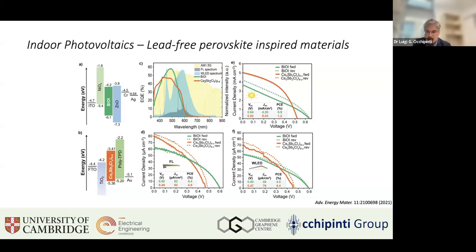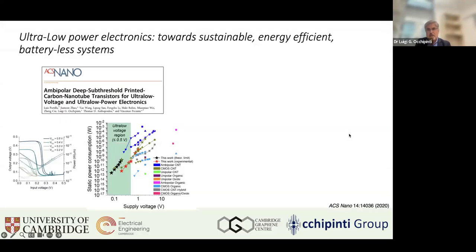Of course, in terms of efficiency, we can't compare this material with the lead-halide perovskite base. It only works when you have to power a very low power consumption unit or electronics. For this reason, we also explored ultra low power electronics. In this work, we reported back in 2020 ultra low power printed electronics as a result of a collaboration with Thomas Anthopoulos and Vincenzo Pecunia.